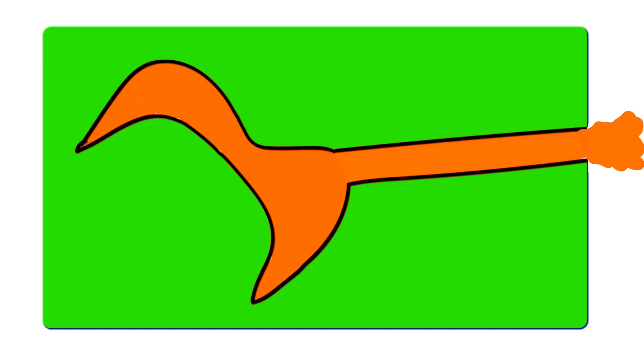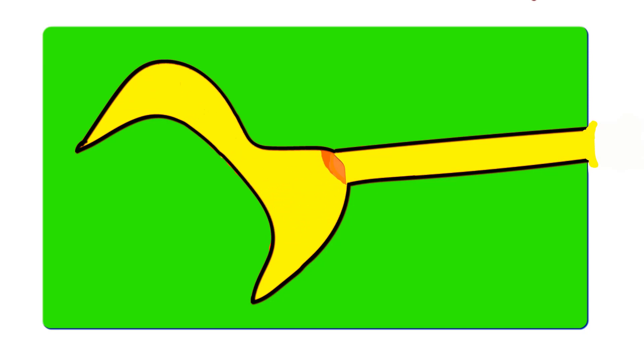This animation shows an example of localized shrinkage porosity. The molten metal enters the mold and the metal starts to solidify. Ideally, it should solidify first at the margins and progress towards the sprue. But since the temperature of this mold is lower than the recommended temperature, the sprue solidifies first, restricting the entry of molten metal into the mold to compensate for shrinkage. When the metal in the mold space solidifies, the junction of the sprue and the mold is the last to solidify, and it is at this point where the porosity is seen.